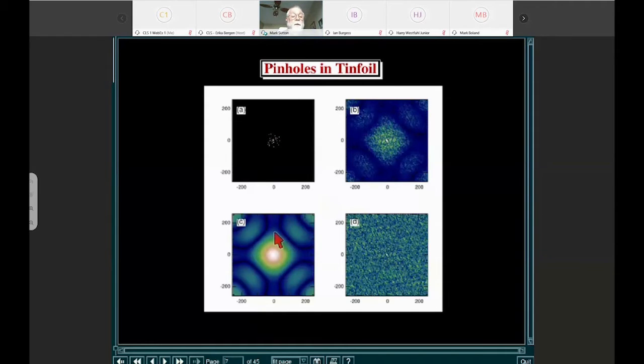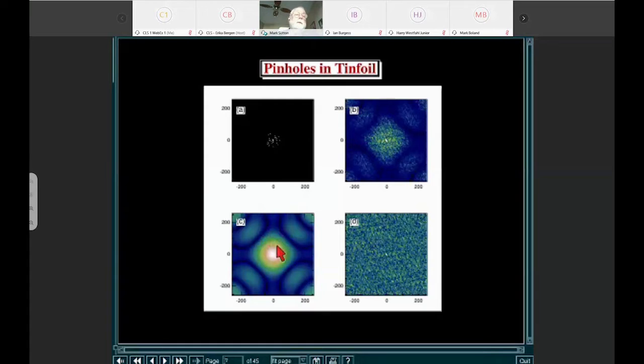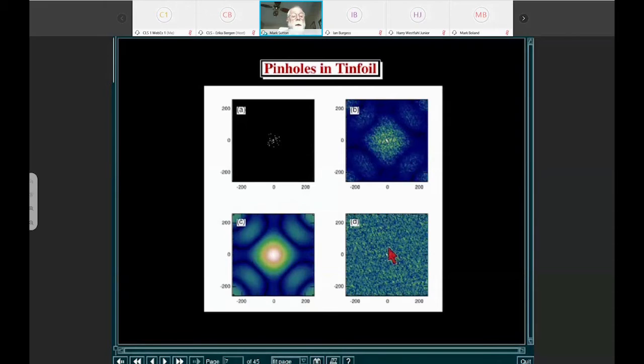So this measures the particle size, and that's usually one of the things that we're interested in. But there's also this very rapidly varying diffraction pattern. That corresponds to a length scale. What length scale is that? That length scale is 2 pi over the size of the diffraction volume that you're trying to study. And when you have lots of speckles associated with the scattering pattern, you can very generally decompose the scattering into the incoherent part, which is what we would normally measure with an incoherent beam, and the coherent part, which is the speckle pattern.